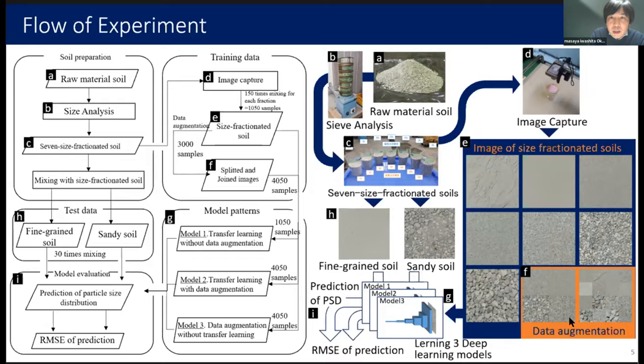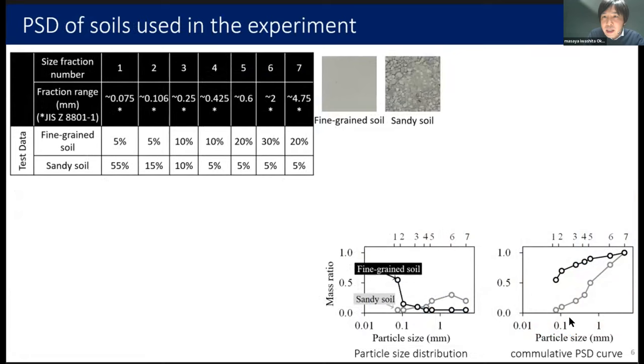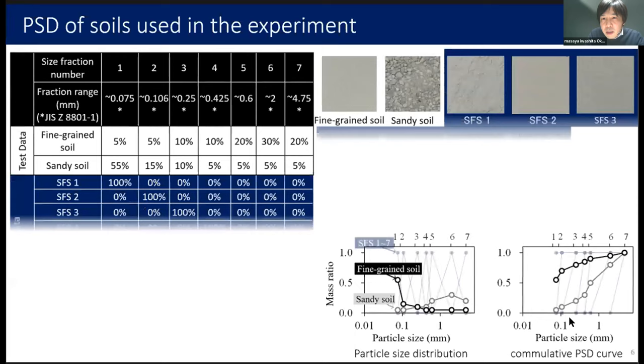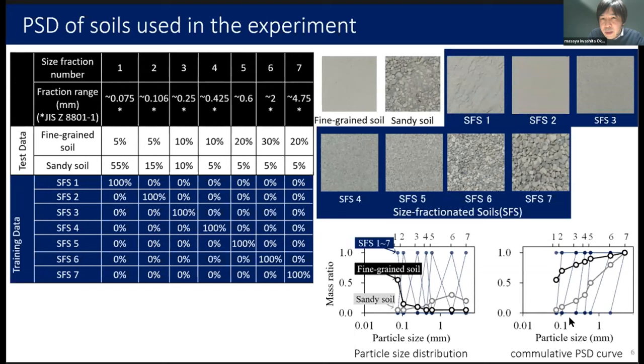Next, the particle size distribution of soil used in the experiment is described. The sieve is divided into seven fractions according to JIS from less than 0.075 millimeter to 4.75 millimeter. Sandy and fine-grained soils are composed of a minimum 5% of particles from each fraction. Fine-grained soil is composed of 5% fine grains, and sandy soil is composed of 55% fine grains. Images of 7 grain size fractionated soils are used as training data for deep learning.